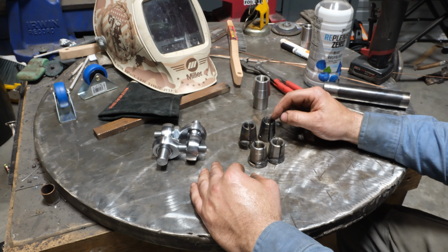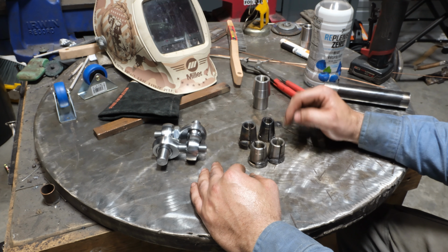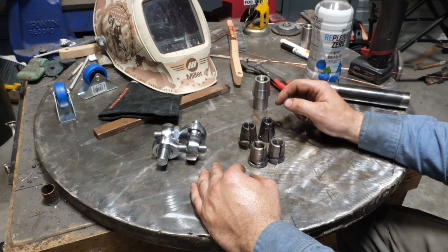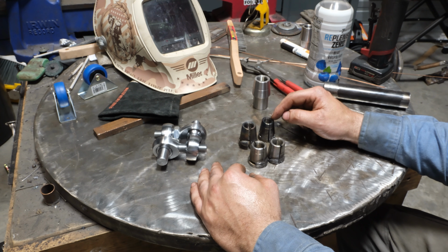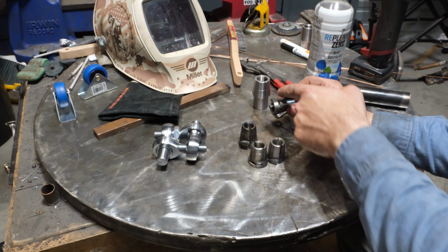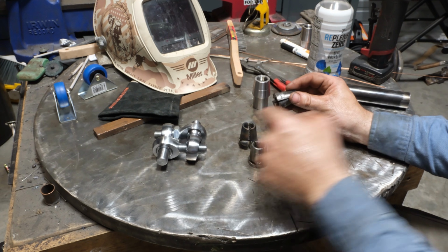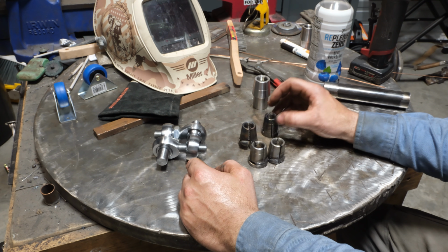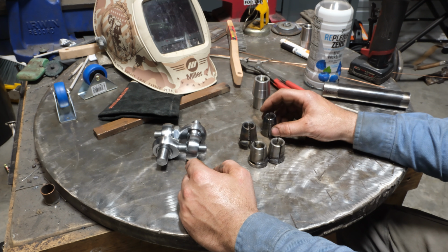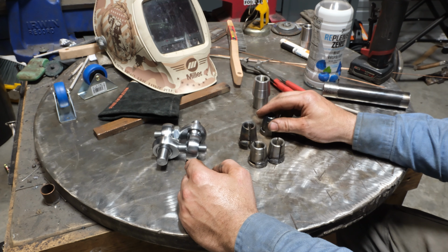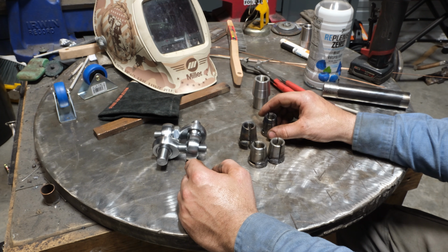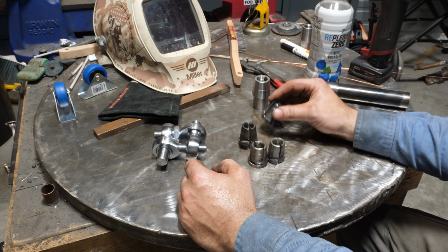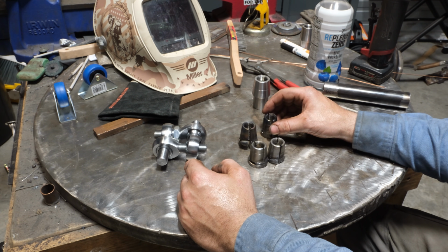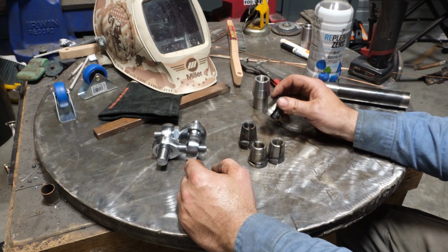Beyond that, one more thing I want to mention that I didn't earlier is that you want to avoid running downhill welds with any of this. And the reason I say that is, especially with MIG, when you weld downhill, you lose penetration. So if this is tipped on its side and you're welding downhill, what'll end up happening is all that root fusion that you may or may not be getting will completely go away. And what can realistically happen is that really poor stack of dimes weld, that could end up being what your weld looks like, even though you weren't stacking dimes as far as the settings are concerned. So that's something to think of. If you can avoid it, avoid it.